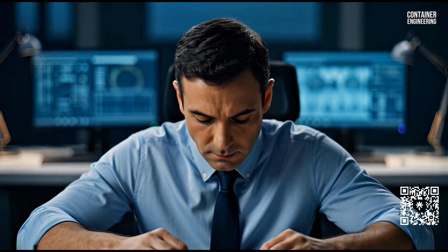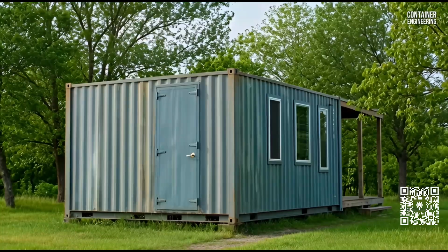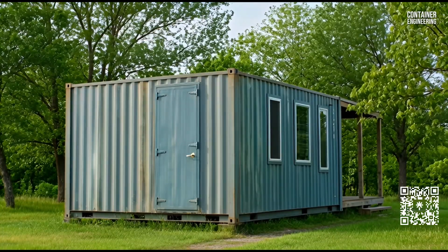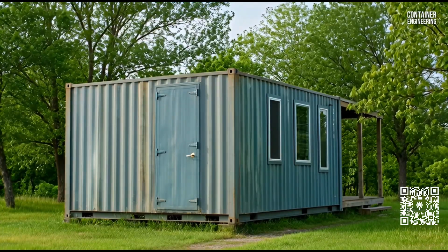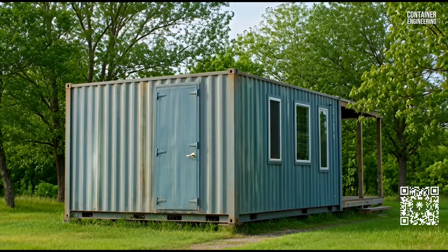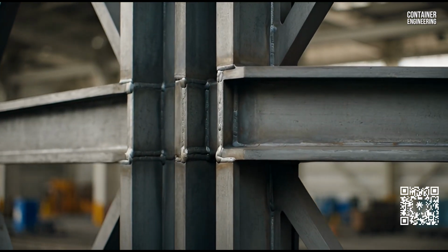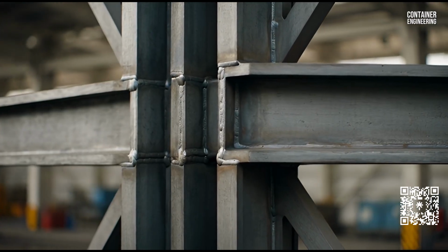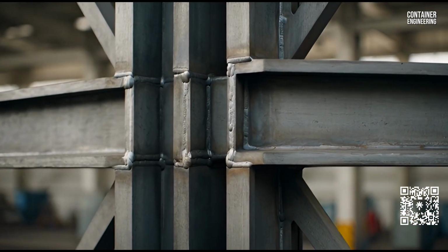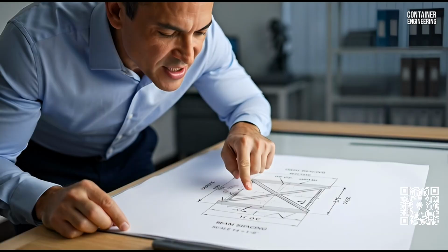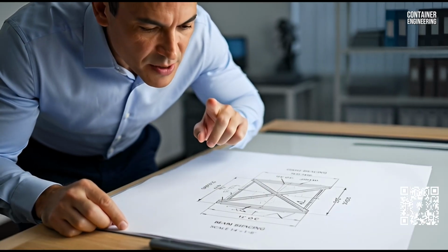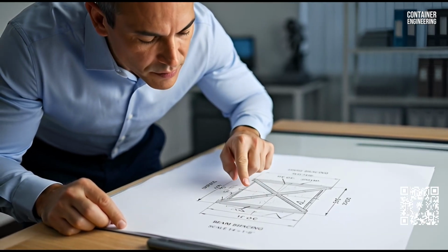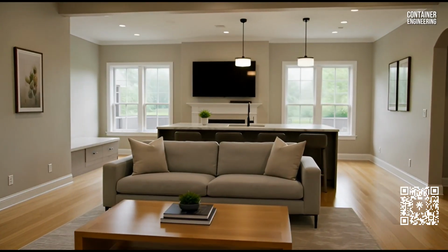For the first year, everything seemed fine, but shipping container steel is Corten steel, which has a yield strength of 50,000 psi but is subject to fatigue under cyclic loading. Every time someone walked across that span, the steel flexed microscopically. After 15 months, we started seeing fatigue cracks at the weld points. By 18 months, one of the cracks had propagated to 6 inches long. I was brought in to assess the damage.